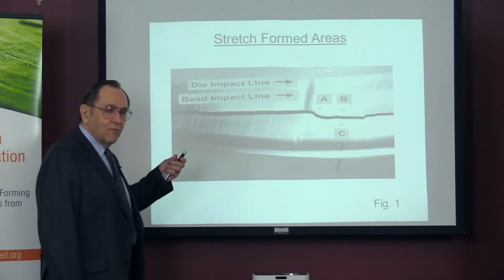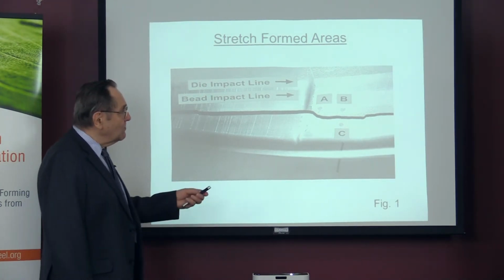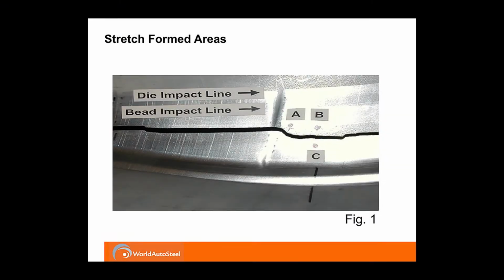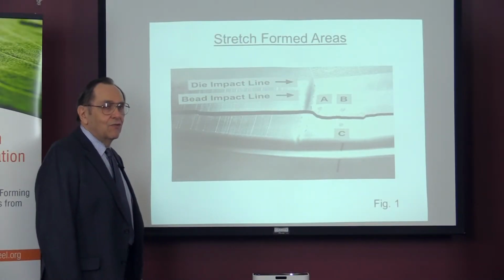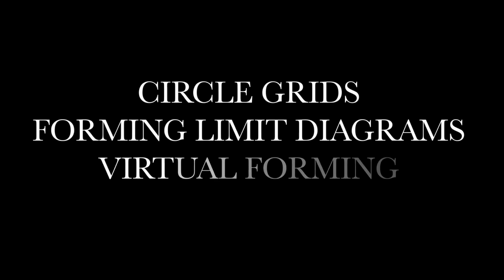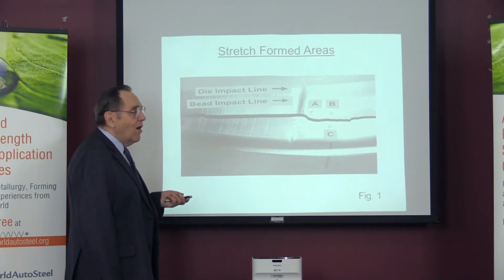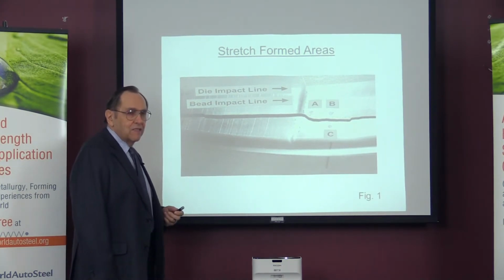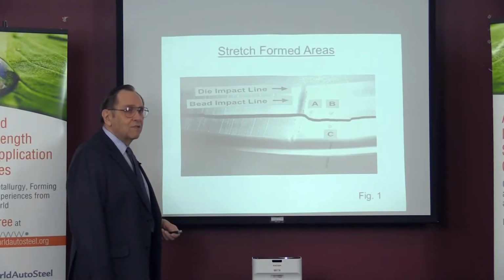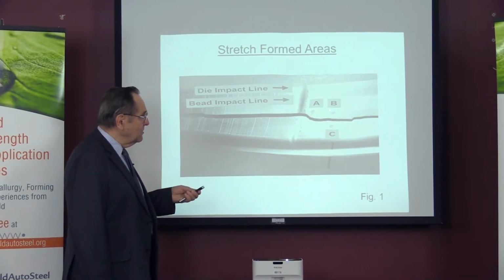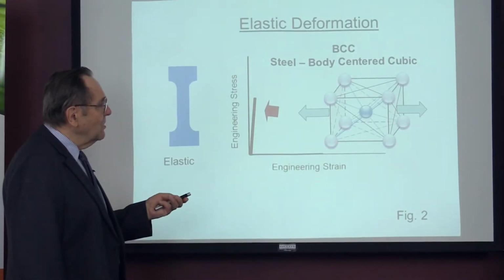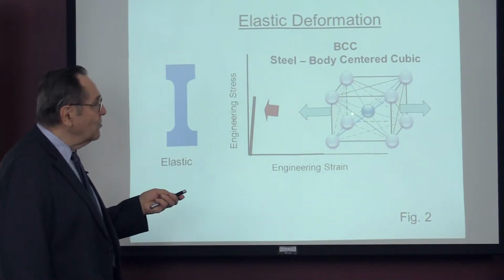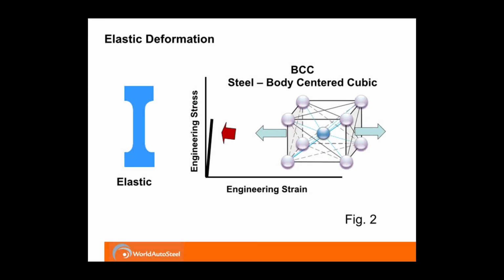Over the centuries that we have been using sheet metal, the problem has always been one of tears and fractures. But we've learned to minimize these through looking at the deformation through circle grids, forming limit diagrams, through virtual forming, and other technologies. Now, the number one problem is the dimensional stability of variations deviating from the specification. And that comes from the elastic stresses, not the plastic deformation that we're used to, but from the elastic stresses which originate in the atomic cube right here, which is the smallest structure of metal.